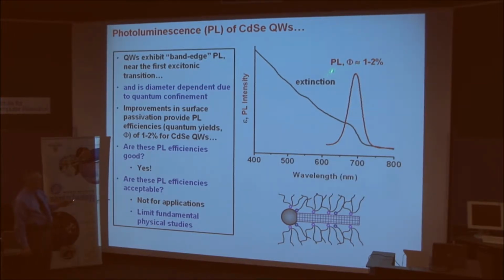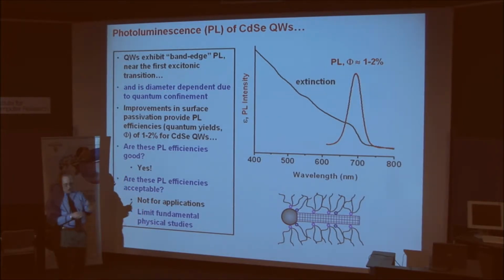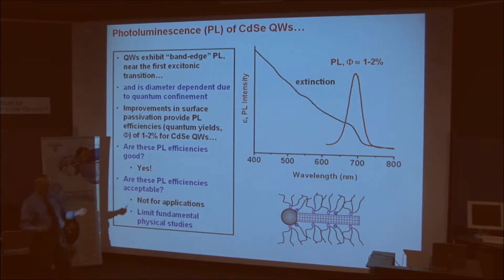So I show here a photoluminescence efficiency in the range of 1 to 2% for CdSe quantum wires, and we actually had to work very hard to get that. And so let me just be clear what a photoluminescence efficiency is. We're generating these excitons or electron-hole pairs with light. So a photon absorbed generates an electron-hole pair. If that electron-hole pair recombines radiatively, the photon comes back out. That's photoluminescence, the radiative recombination.